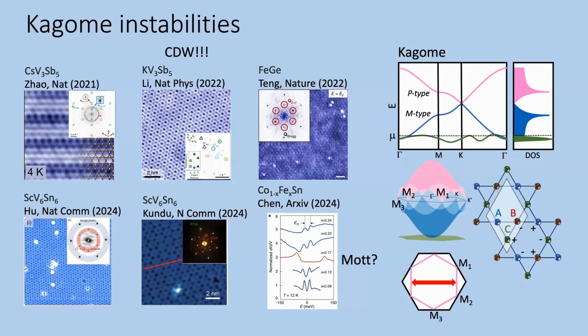What happens in the material that we studied would be different, and the main reason we think that the material that we studied, nickel-3 indium, avoids the fate of a Mott insulator is actually because it has not only a flat band at Fermi, but also light bands. And cobalt tin doesn't have these light bands, so its fate is a Mott insulator. And in our case, we believe we indeed form a strange metal.